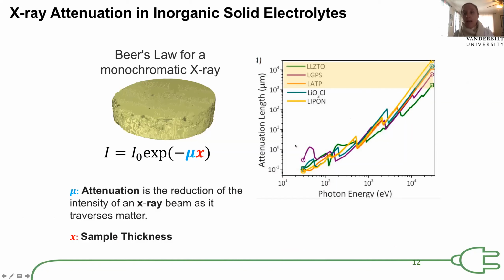Every material interacts differently with an X-ray beam. And so what I've highlighted here is Beer's law, where the intensity or flux through your material is going to be a function of the attenuation, which is materials driven, and x, which is again the experimental design that we're considering. So if I want to design an experiment to look at a battery at realistic length scales, I have to consider this. And I also have to consider the materials that I'm using. What you can see here, at different photon energies, are characteristic examples of solid electrolytes. And we can see that as I get to attenuation scales that are of interest, I have to go to exceedingly high energy levels to probe these material systems. And so this really motivates why we go to a synchrotron.